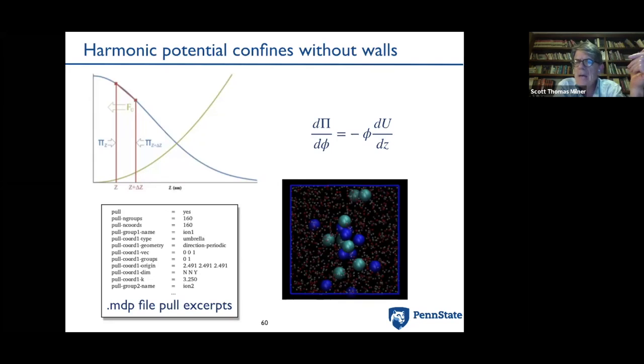And to do this, what we have to do is put every single ion, plus and minus, in a harmonic potential that tends to confine it to the middle of the system with about a 4 kT energy difference from the outside to the inside in order to prepare a decently tall bump in the concentration profile. And then average for a right smart time to measure a quite nice concentration profile.